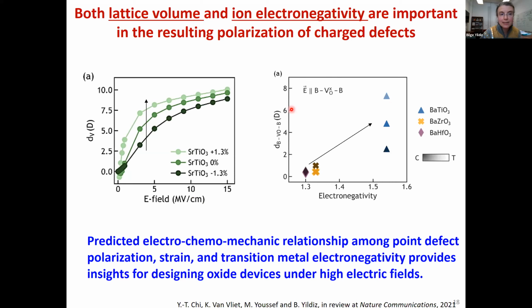And so in summary, we're finding that the lattice volume that you make available for polarization, as well as the neighboring ion electronegativity, are comparably important in giving rise to polarization of charge defects under electric fields. And this is really a problem where the coupling of electrical properties with chemical properties and mechanical properties is prominent. So that's why we're referring to this as an electro-chemo-mechanically coupled relationship that defines the point defect polarization as a function of strain and transition metal electronegativity. It is important for us to see, because this way we understand the material properties under functional conditions more accurately.